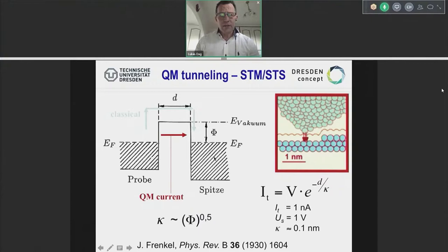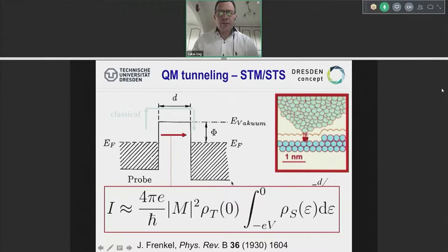The difference in the work function between these two materials. So that means the probability of an electron to change from A to B is always proportional to phi, or the difference in phi, and hence we already have a good possibility of how to measure that. So if you put this more into math, what we come up with is this equation that says, okay, the tip has some density of states, rho, the sample has some density of states, rho, and it's a question of how these two things really want to talk to each other. Or in more common words, it's an overlap of wave functions or of orbitals, atomic orbitals, or later, as you will see, also molecular orbitals. And that's the whole glory of the thing. If these two guys want to overlap, then they can exchange electrons, they can also exchange other quasi-particles. And once we learn how they do so, we learn something about their chemistry. I don't want to go too much into the detail here, because that's a very complex formula already, because this M is non-trivial to solve.